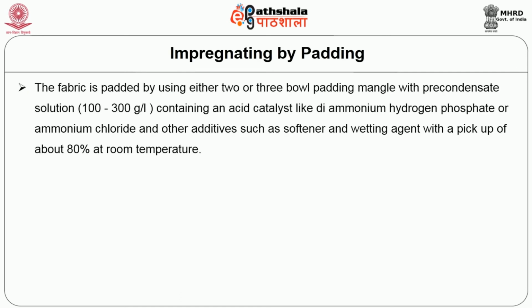The fabric is padded by using either 2 or 3 bowl padding mangle with precondensate solution 100 to 300 grams per liter containing an acid catalyst like diammonium hydrogen phosphate or ammonium chloride and other additives such as softener and wetting agent with a pickup of about 80% at room temperature.